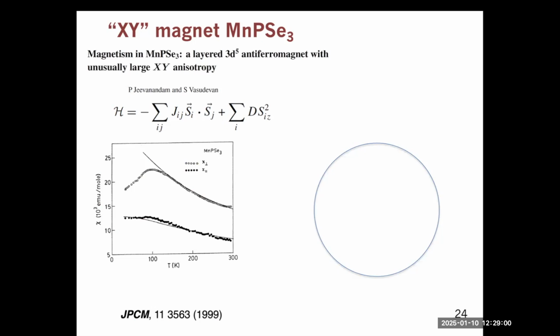Well, that's what this paper says. But anyway, this is basically the evidence that magnetic moments are in the plane. Where spins are, we don't know. The G factor can be anisotropic. What we measure are magnetic moments, not spin. Magnetic moment is related to spin with the G factor. If the G factor is strongly anisotropic, spins can be isotropic, but magnetic moments not.